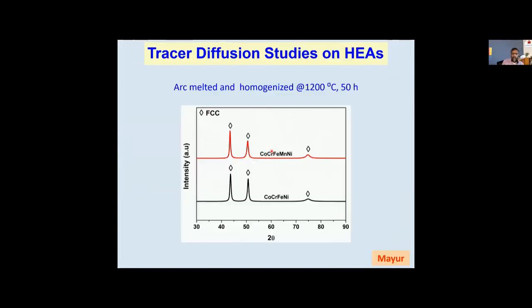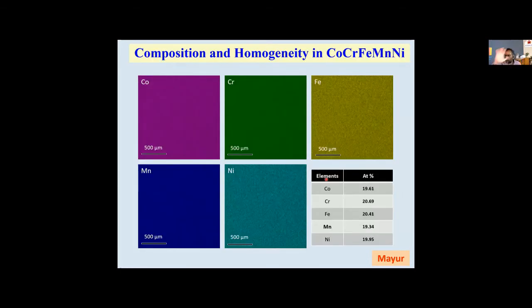The next question we wanted to understand is: I have these many alloying elements inside — how do each of the elements diffuse into each other? Can I predict the diffusivities in such a multi-component alloy? We made two high entropy alloys — one is a four-component alloy, one is a five-component alloy — all in equal proportions. XRD patterns show a single-phase FCC in both cast and homogenized alloys. Looking at elemental mapping in the SEM, all five elements are uniformly distributed with no segregation, all very close to 20%. So I made a high entropy alloy with equal proportions of each element.